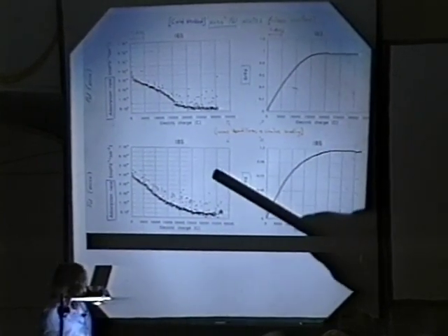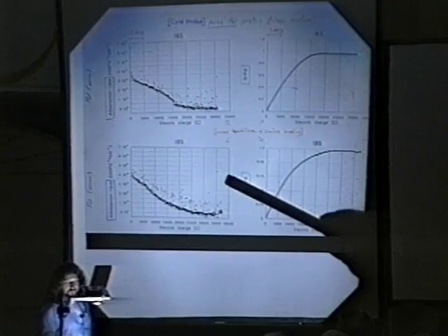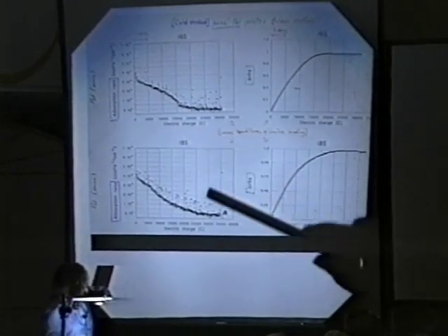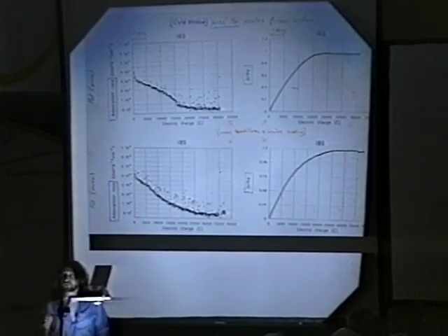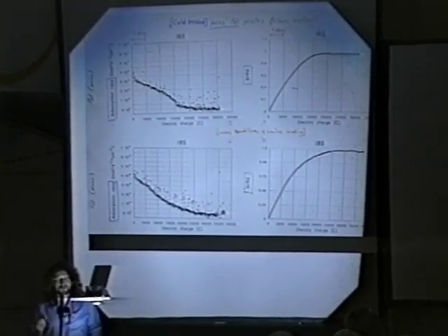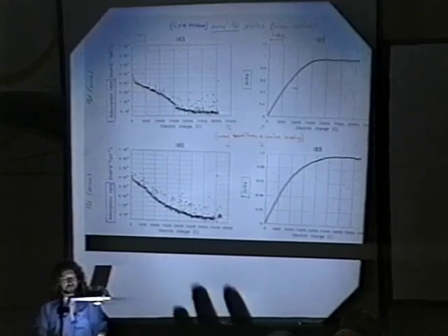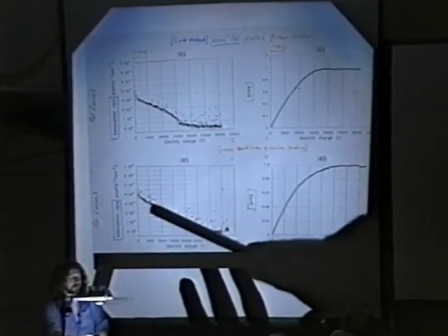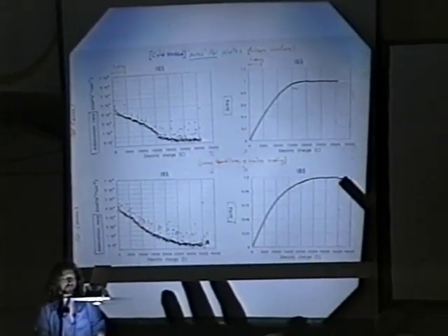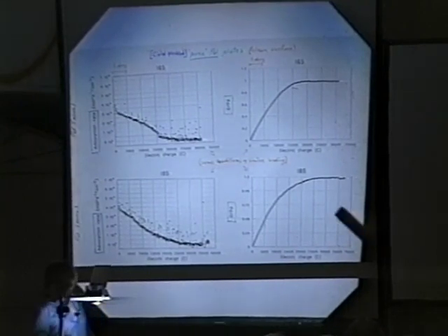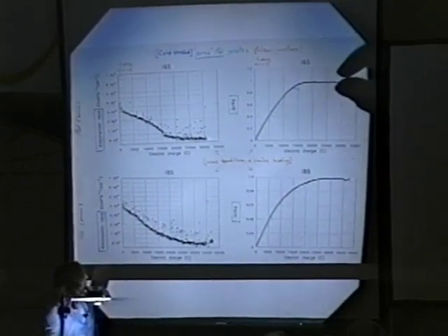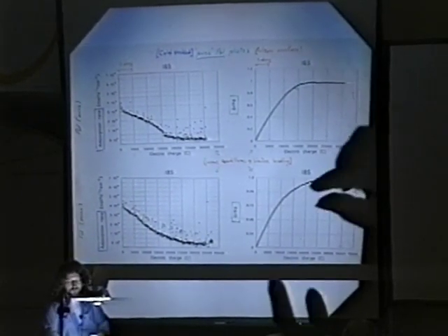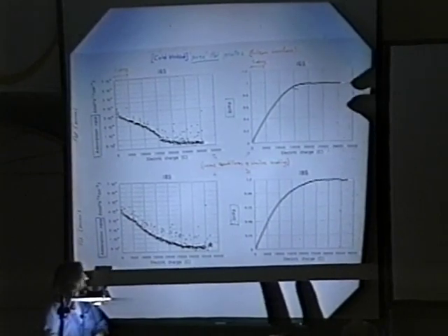I show also this other one. This is another, different plate, in exactly the same working conditions, and we have more or less the same absorption rate and more or less the same loading. So the experimental error can be something like less than 10%. So we can write here a band.